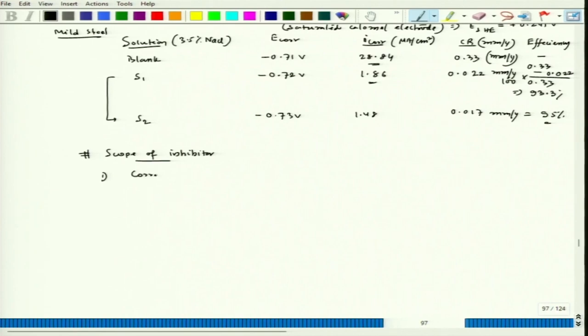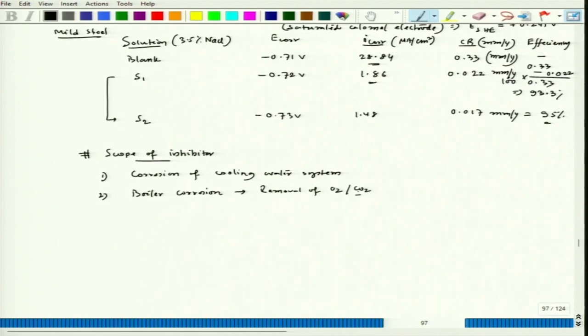One is corrosion of cooling water piping system, like heat exchangers or distribution line. Boiler corrosion can be reduced using a small dose of inhibitor, like removing CO2 or oxygen by water treatment. Deposits may also form by suspended solids, so that can be avoided. So removal of O2 or CO2, those kind of dissolved gases can be removed, and boiler corrosion can be minimized by the usage of inhibitor.